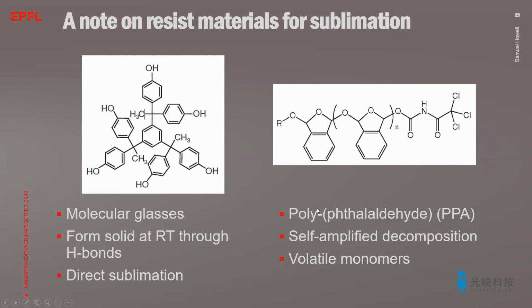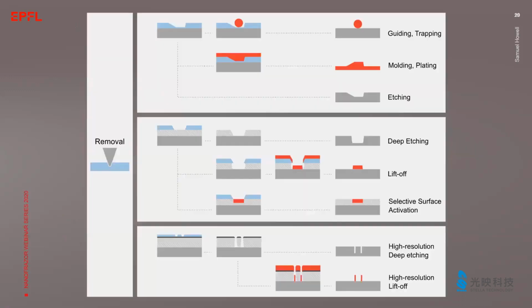Besides the clean decomposition of this resist, it exhibits also a reasonable shelf lifetime and can resist chemical etching with standard transfer processes. Hence, it is currently the most used thermal resist. And the examples that I'm going to show in the following slides are often performed with polyphthalaldehyde. So for removal, a large process library exists already. Depending on the number of layers, different resolutions and modifications are possible.